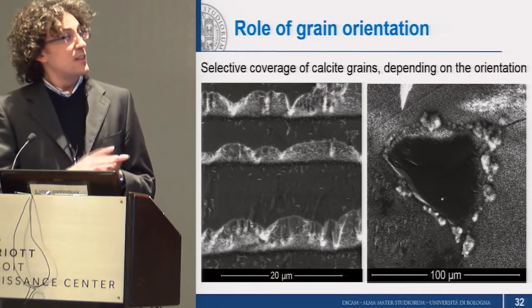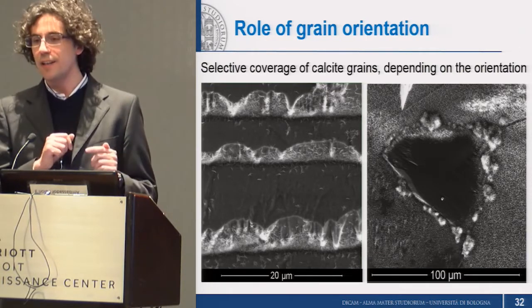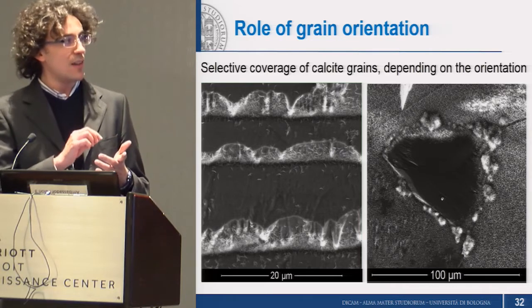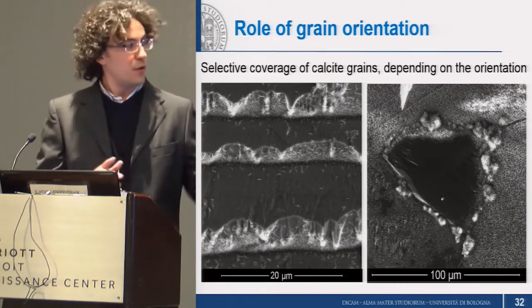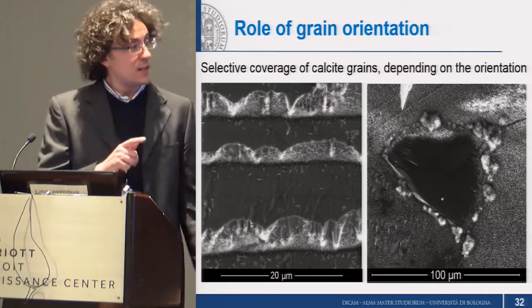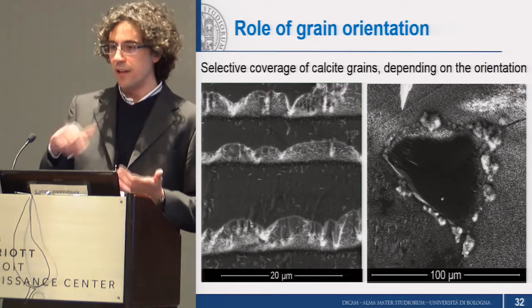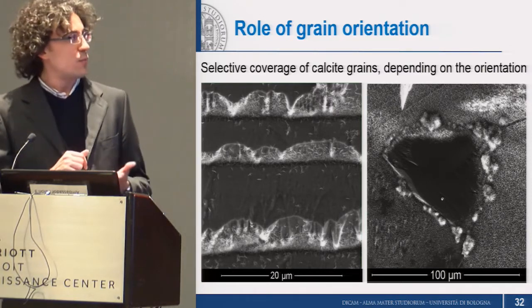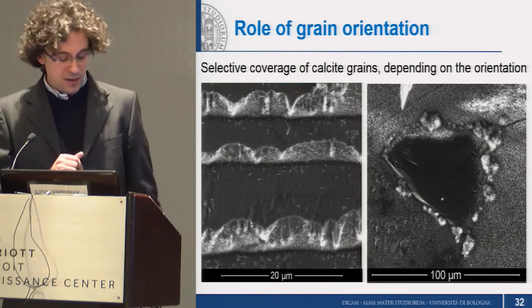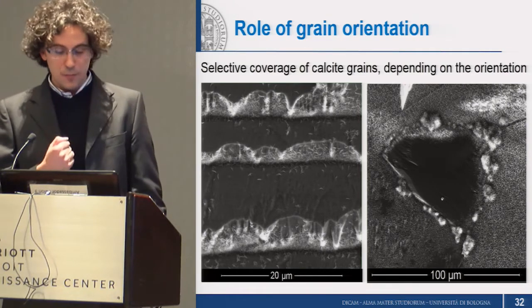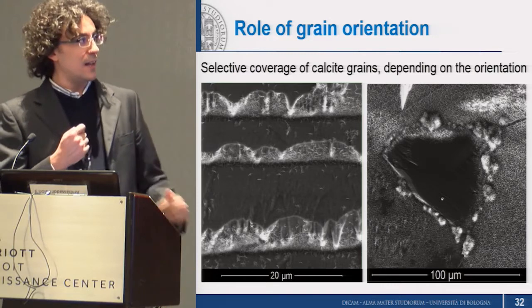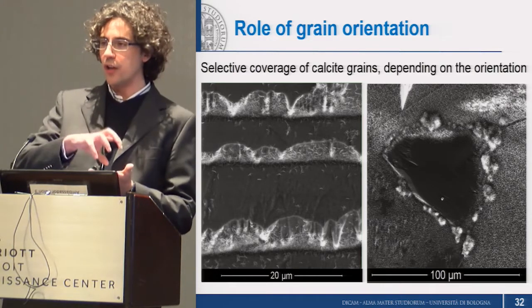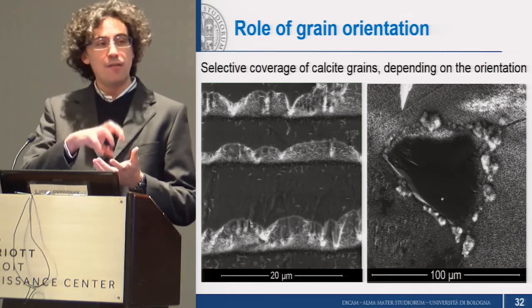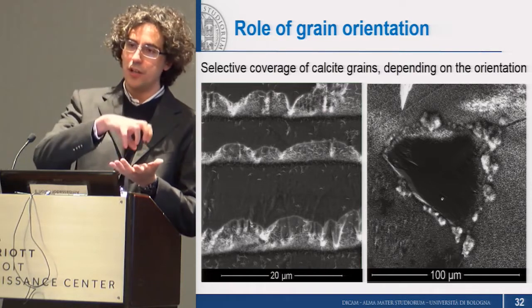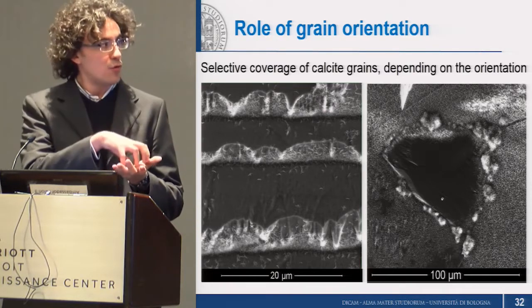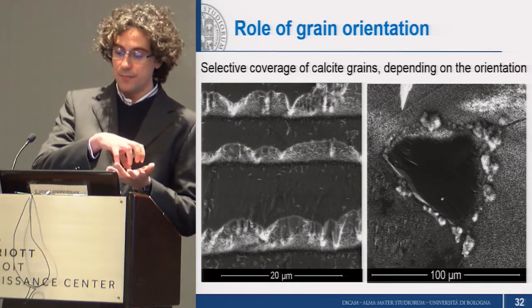that I mentioned, still, looking closely, there are some grains that are completely bare. So for instance, in the right image, even if all the surrounding grains are perfectly covered with HAP, and in other cases on the left. And so the problem in this case, we think, is that the orientation of the calcite crystals has a very strong influence on the possibility of HAP, of hydroxyapatite, to grow on top of these grains.